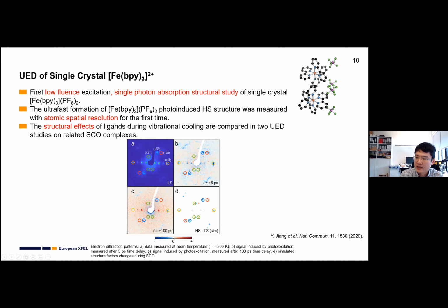So we can see this one is similar to what I showed for the iron PM-AZA. This is the diffraction pattern for iron bipyridine. And this is the signal after 5 picosecond time delay. This is the signal after 100 picosecond time delay. This one is the simulated structure factor change during the spin crossover.